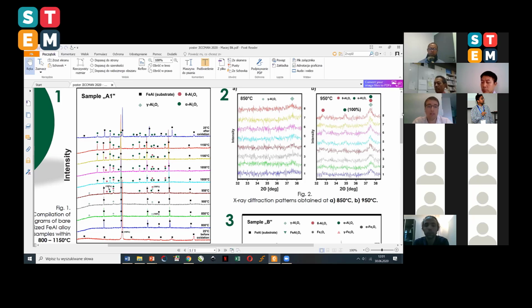So it is a really interesting study because we can show the oxidation and some phase transitions not only as a function of temperature but also as a function of time at the specific temperatures. So one single measurement, which is shown on the right, lasted for 30 minutes, and it is like an average result of these 30 minutes of the investigation.